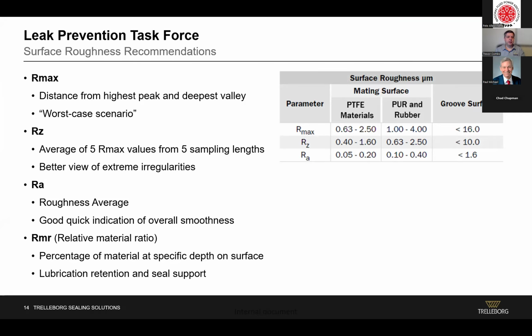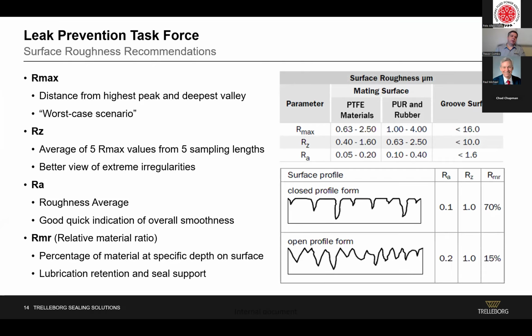And then another important parameter is the relative material ratio. The relative material ratio is basically a percentage of the material at a specific depth on the surface. So you're looking to do a cross-section of the surface at a level that the seal is most likely going to ride on for most of its life. It's going to break down some of those peaks, and then it's going to ride on a surface that's just a little bit below the top of the surface before it's been broken in. And that's what the RMR is trying to provide for you, an understanding of how much support the seal is going to have, as well as how much lubrication retention the seal is going to have.